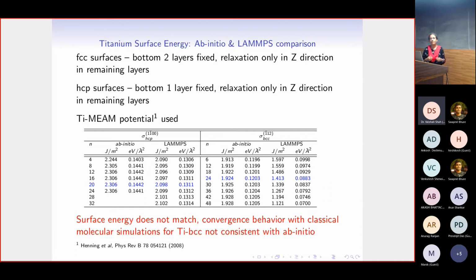Which means that if I do the solid-solid interface energy calculation using the classical simulation, I really have no confidence in the results I would be obtaining, because neither the surface energies match nor do the behaviors of the surface energies match. So then what do we do? Because we can't do this by ab initio, and now it looks like we can't do this by classical simulations. So is there no way out of this?